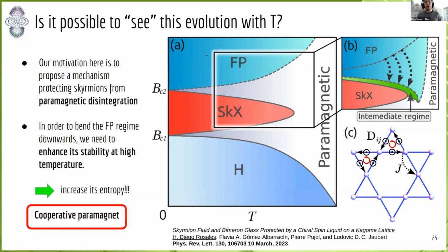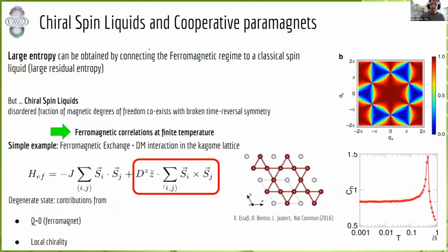This is a complicated situation, but we have in mind one possible solution, a cooperative paramagnet. The idea of a cooperative paramagnet is a disordered phase, but with large entropy. And it presents in particular dipolar correlation at low temperature. The manifestation of the dipolar correlation is seen, for example, in neutron scattering or a structure factor in this specific phase. You can see the characteristic pinch points at specific positions in reciprocal space, which are a manifestation of the dipolar correlation. In particular, if we use this Hamiltonian with ferromagnetic exchange coupling plus the Dzyaloshinskii-Moriya interaction along the Z direction, you will obtain a particular kind of spin liquid, which is a chiral spin liquid.